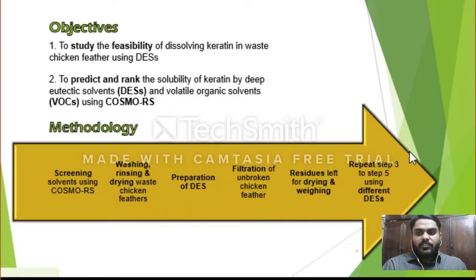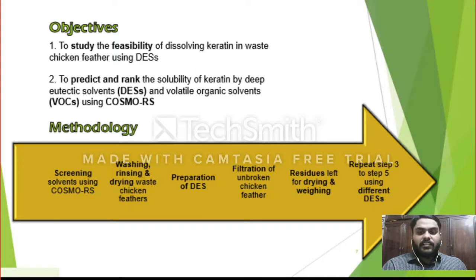The methodology of this project involves first screening the solvents using COSMO-RS, second washing, rinsing, and drying waste chicken feathers, next the preparation of DES, then filtration of unbroken chicken feathers with the residues left for drying and weighing. Lastly, the steps are repeated with the preparation of different DES.